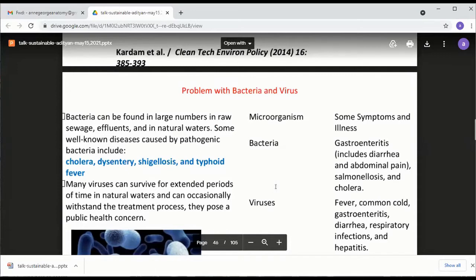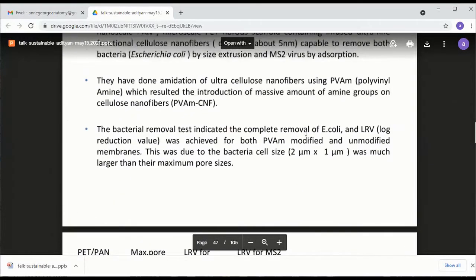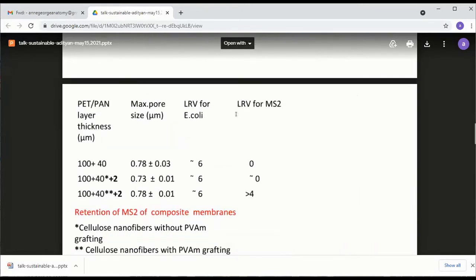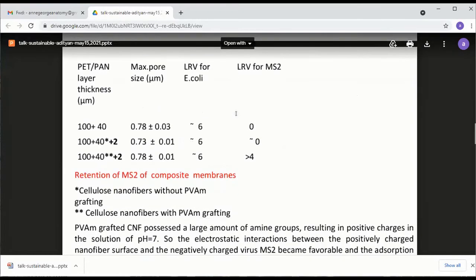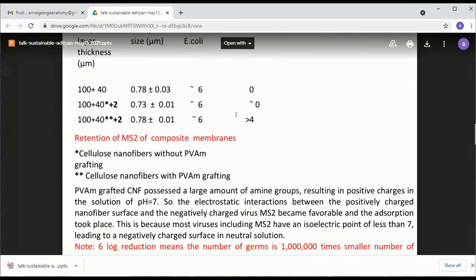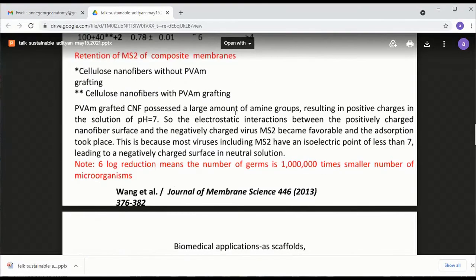But if you want to catch viruses, they are very small, nanometer size. They usually try to get away from the filter. If you want to remove viruses, you have to do some chemistry. The chemistry is, again, reacting with the polyvinylamine. You introduce amine group on the surface of nanocellulose. You all know that these viruses have a protein envelope which is negatively charged. So you can have electrostatic interaction between the virus and the nanocellulose surface. And you can see the logarithmic removal values, the LRV values. They're pretty good. So you can remove viruses, bacteria, etc.